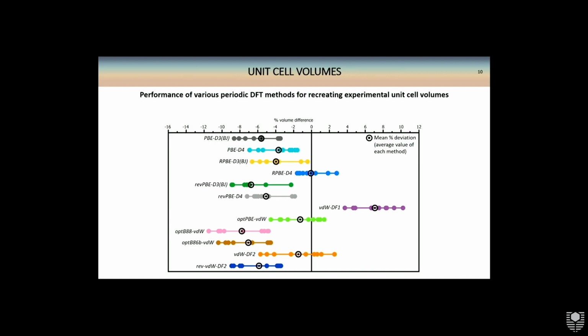To begin with, we were looking at how well the different levels of theory perform in terms of recreating experimental unit cell volumes. This is a good measure of how well a level of theory recreates the geometry of a cell. This plot shows the 12 different levels of theory in terms of a percentage volume difference between the calculated results and the experimental unit cell volume. The black circles are the mean percentage deviations of each level of theory, that is to say, the average value of the method.